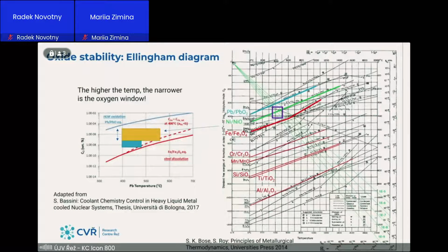This diagram shows you the stability of oxides, and we are limited with this oxygen dosing from the top by solubility of lead oxides. And also from the bottom side, we are limited by dissolution of these iron oxides that are protecting our structures. You can also see here, if you go down with oxygen, that in the down direction there is a stability of silicon oxide or alumina oxide, so they will sustain very low oxygen concentrations at very high temperatures, and that's why they were chosen as coatings or as additions to these special alloys that are resistant to this media.